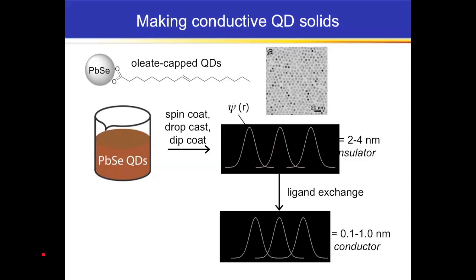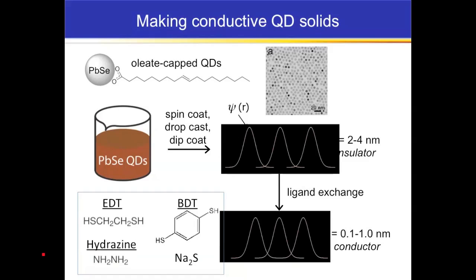So what we need to do to get a conductive material is to do partial or total ligand exchange and remove this oleate molecule and replace it with something else that's much shorter. In the field, people use a variety of organic ligands to do this. For example, ethane dithiol is a nice 2-carbon chain, much smaller, of course, than oleic acid is. And so that allows the quantum dots to move closer together. You get better wave function overlap, interdot distance on the order of, say, 0.1 to 1 nanometer, and you get a conducting material in that case.